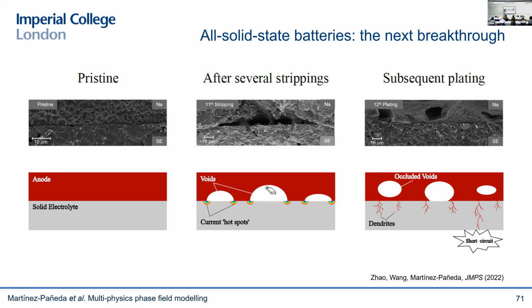And when you remove that lithium from the anode, you create these voids here. And every time you charge the battery, you have plating. You deposit lithium again in the anode, and then you reduce the size of those voids. And understanding how those voids evolve is critical, because at the edges of those voids, we have what we call current hotspots, so regions where the current becomes very high. And as a result of that, in the next plating cycle, you deposit too much lithium and you get these dendrites that grow, and the short circuit could kill the cell, the battery.